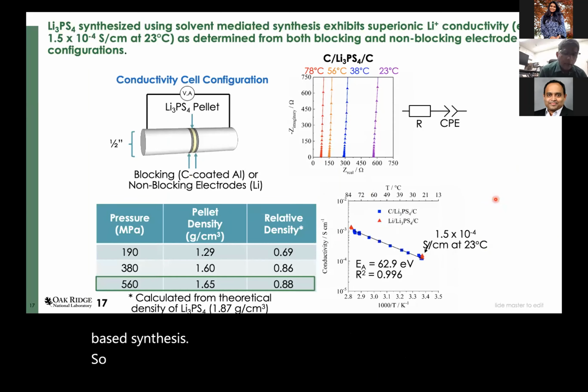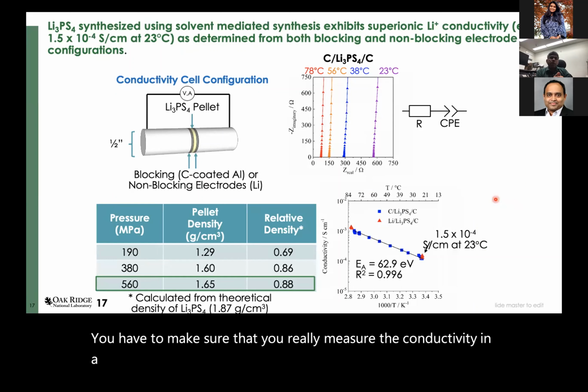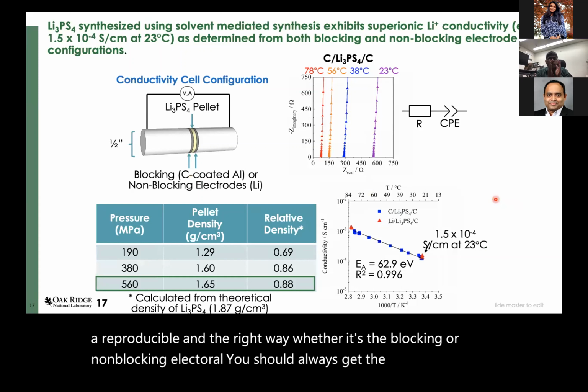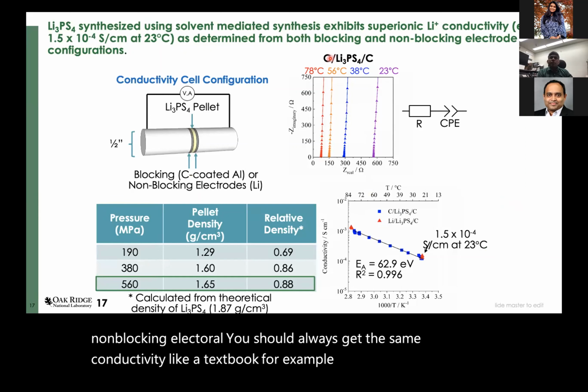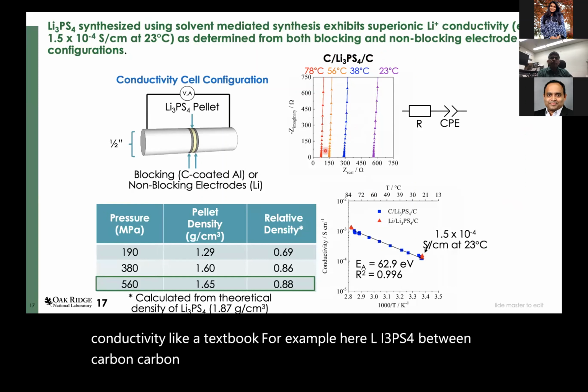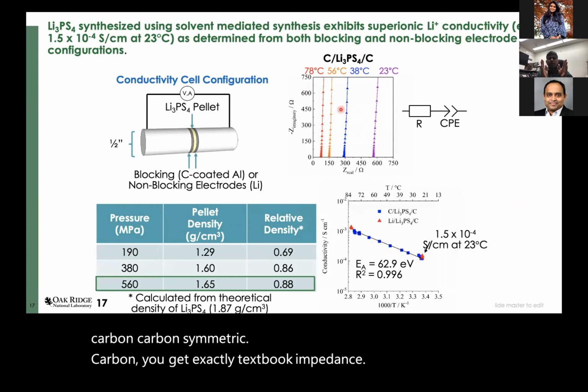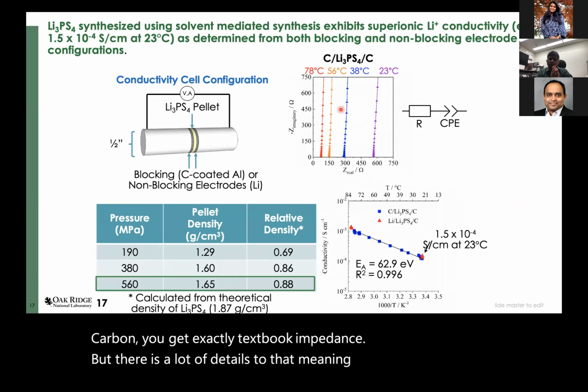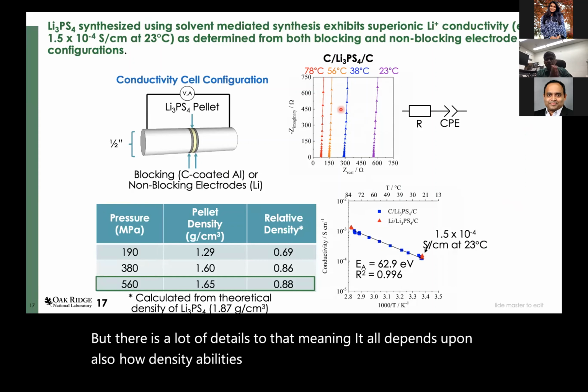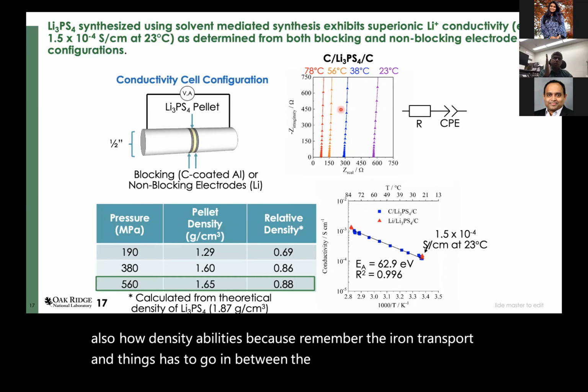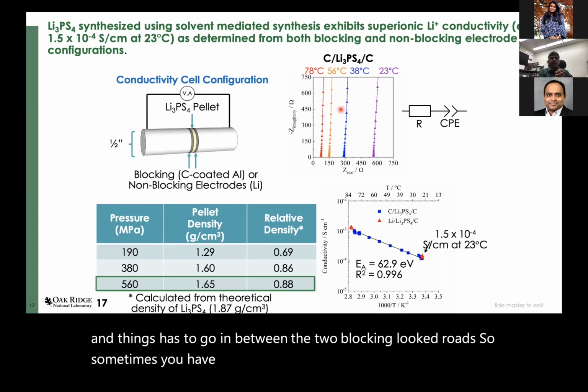After you make this, you have to make sure that you measure the conductivity in a reproducible and the right way, whether it's a blocking or a non-blocking electrode. You should always get the same conductivity, like a textbook. For example, here Li3PS4 between carbon-coated aluminum symmetric electrodes, you get exactly textbook impedance. But there are a lot of details to that. It all depends upon how dense your pellet is, because remember, the ion transport has to go in between the two blocking electrodes. So sometimes you have to optimize and make the pellet very dense so that you have the right conductivity.